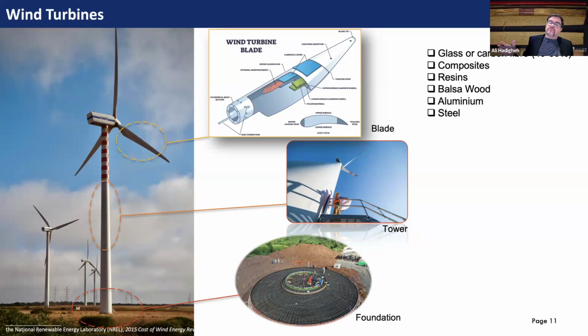So if we look at those turbine blades, the size dictates what sort of materials we have to use. Is it carbon? Is it glass? Is it a combination of them? Is it a hybrid system or not? So 40 to 50% of this blade is made of that composite. And recycling of this is extremely difficult. And we know why, most of us know why that is difficult. When you cure the composite, separating that fiber from the epoxy is extremely difficult and energy intensive.